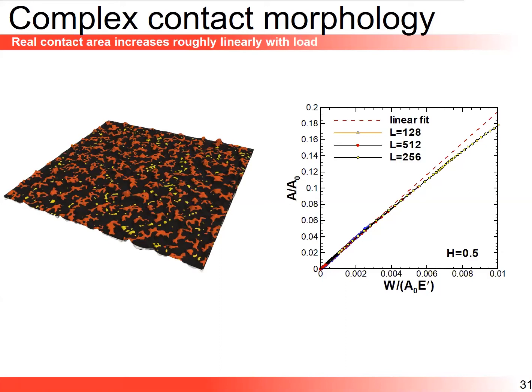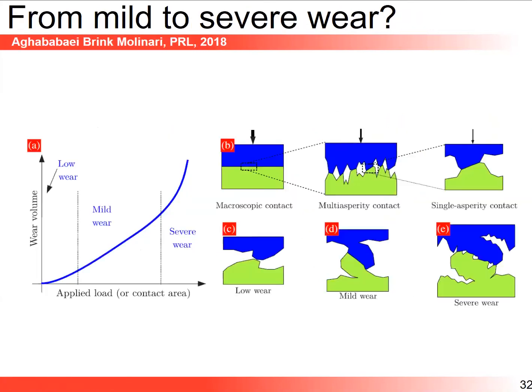And it's clear to us at this point that they have to interact, they are nearby, right? They cannot be treated as isolated microcontacts. And in fact, there are observations in the literature where regimes change as a function of load. It's known that as you increase the load, you transition from what is known as a mild wear regime to a severe wear regime. And what I want to give you a hint at here, with the schematic, is that as you increase the load, you populate more and more your interface with microcontacts. They start to interact.